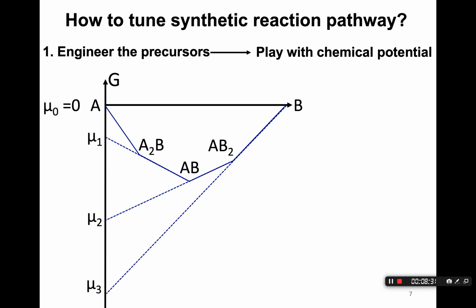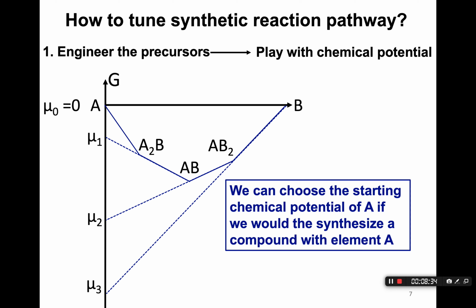So this is a simple story that may give you some hint about what we should do. We are essentially picking up different compounds in the lowest energy envelope, which we call convex hull, and we're using that to engineer the chemical potential of element A. And we actually have much more to do here. We don't only have 3 compounds. We know we have these metastable polymorphs, right? So the empty space between A and B, as well as the envelope, holds a large amount of precursors that we can deal with. Usually we're going to have hundreds or even thousands of them, depending on which composition space you're looking at. So that is actually a very large combinatorial space.